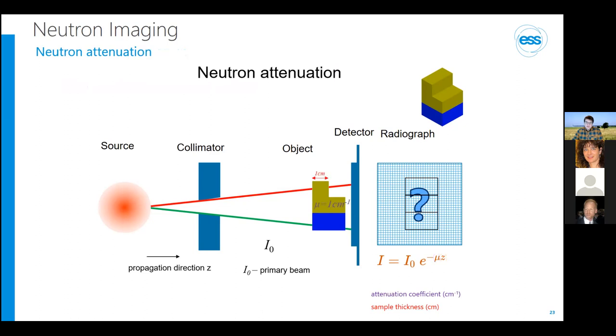So now let's assume we have 1 centimeter of material with an attenuation coefficient of 1. This means that of the 100% intensity I0, only 37% would be left on the other side. And if it now passes through 2 centimeters of material, then only 13.5% of the initial beam intensity would be left. The thicker part of the yellow material will hence appear darker than the thinner part.